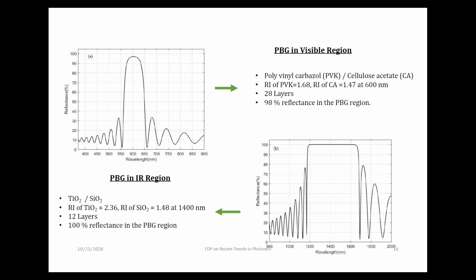But when it comes to the optical region, say I want to get a high reflection at 600 nanometers, what will be the thickness of the layers? The layers will be around 150 nanometers thick. To make a layer of 150 nanometers precisely is a difficult task, because the different methods are either costly or need very careful optimization. So that is one difficulty when you want to go down in scale. Maxwell's equations are scalable. There is no fundamental length scale. You can scale your Maxwell's equations to any range in the electromagnetic spectrum. That is good. But when it comes to practical implementation, making the layers or machining the material itself can pose a problem.